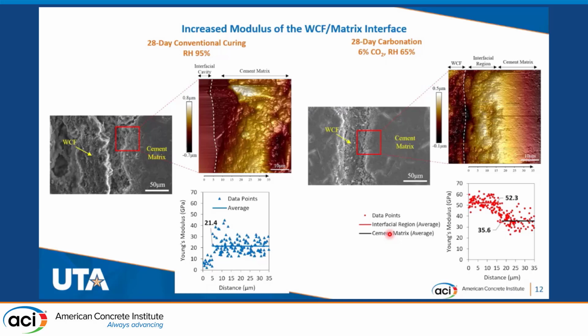We further examined the properties of the interfacial area, and actually we evaluated the mechanical properties between the fiber and the CSH. We used a nano-IR AFM to evaluate the modulus of elasticity of the interface between the fiber and matrix for the non-carbonated and the carbonated specimens. And actually we conducted the quantitative nanomechanical property mapping.